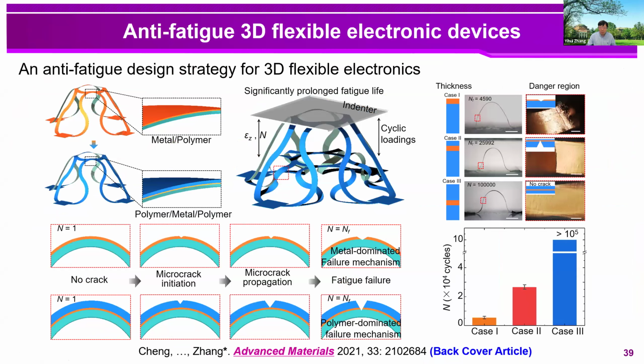And to increase the reliability of the 3D electronic device, we have developed an anti-fatigue design strategy. And here, the key is to convert the metal-dominated fatigue failure into the polymer-dominated failure. Our fatigue experiments showed that even by adding a very thin polymer layer, the fatigue life can be significantly increased, for example, to above 100,000 cycles.